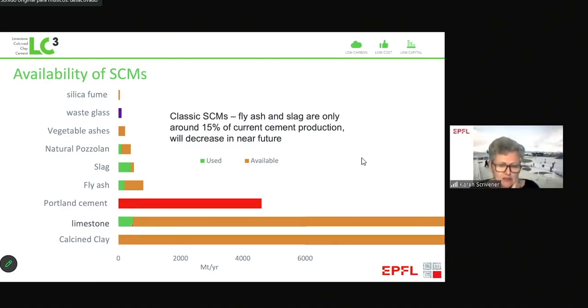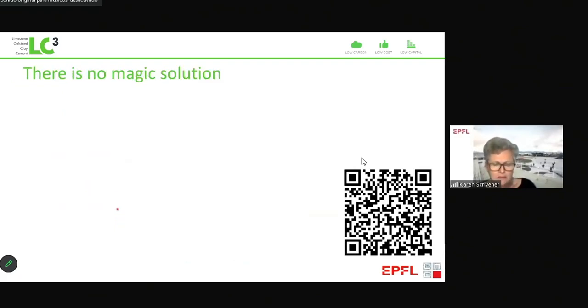Well, we've got a lot of limestone, but the problem with limestone is it's very, very slightly reactive. And therefore, if we go above substitution levels of about 10–15%, we'll simply have a dilution and we'll end up using more cement. What we have got is clays, and clays we can calcine, that's to say heat to around 800 degrees, and then they become very reactive materials. And because they're very reactive, you can go to high substitution levels. So you can go to much higher substitution levels than you can do with, say, fly ash or natural pozzolans.